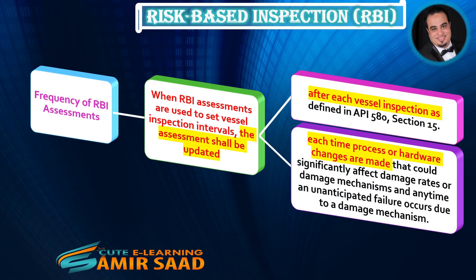Frequency of RBI Assessments. When RBI assessments are used to set vessel inspection intervals, the assessment shall be updated after each vessel inspection as defined in API 580, Section 15; each time process or hardware changes are made that could significantly affect damage rates or damage mechanisms; and any time an unanticipated failure occurs due to a damage mechanism.